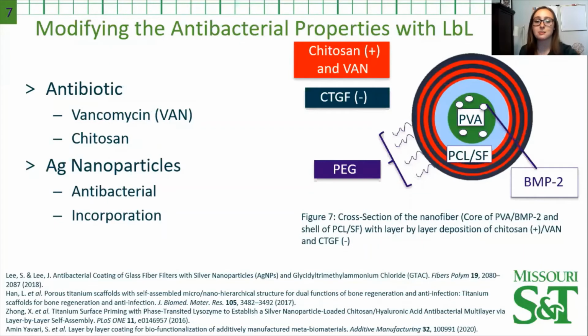Bacterial infection is a common problem with implants that are placed inside the body. If a biofilm of bacteria forms, the implant is likely to fail, and that's a large issue. So we commonly use antibacterial agents to slowly release from the design to prevent bacterial adhesion. This is beneficial if done correctly, however, it has some drawbacks. They include possibly creating more resistant strains of bacteria or inactivity of the agent. But it has been shown that vancomycin, an antibiotic, can be incorporated into chitosan. I propose that the antibiotic be incorporated into this design along with each layer of chitosan.